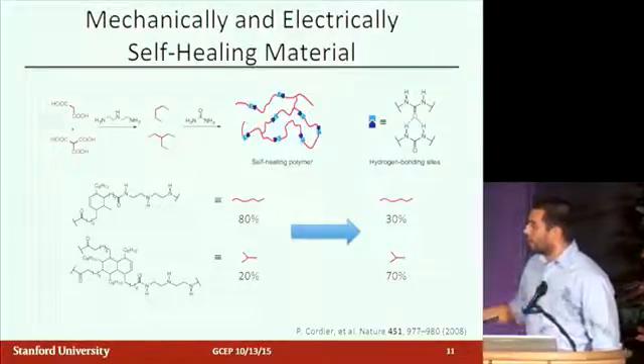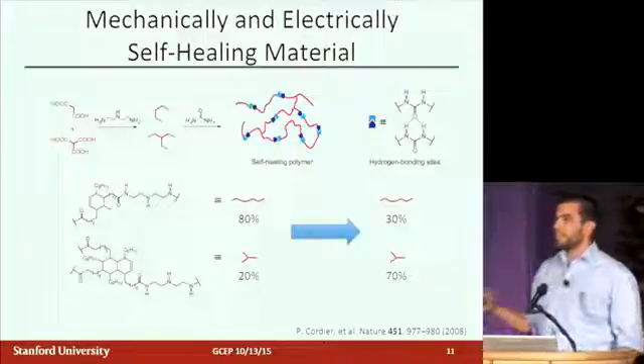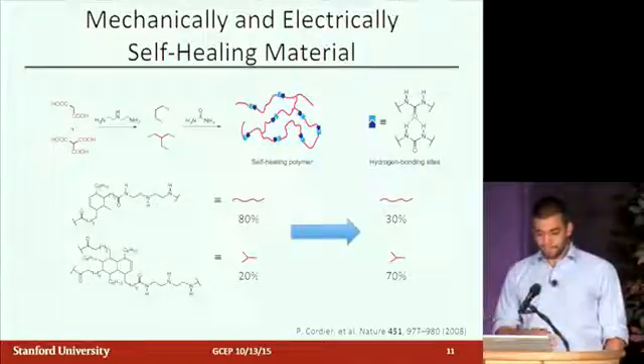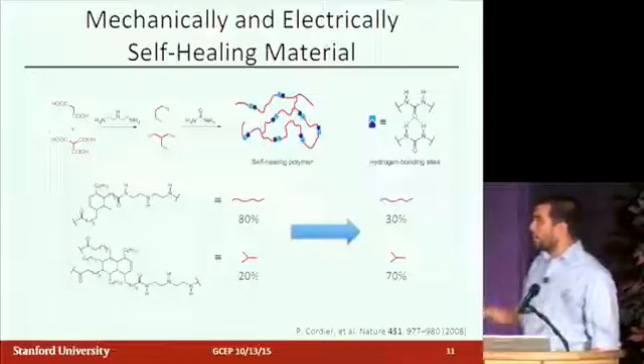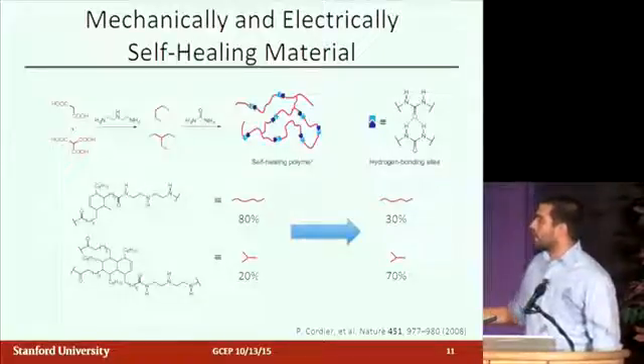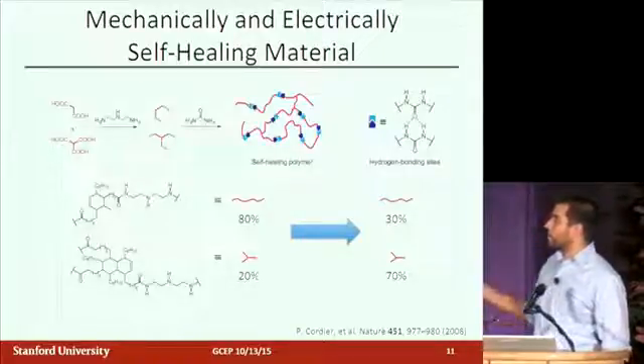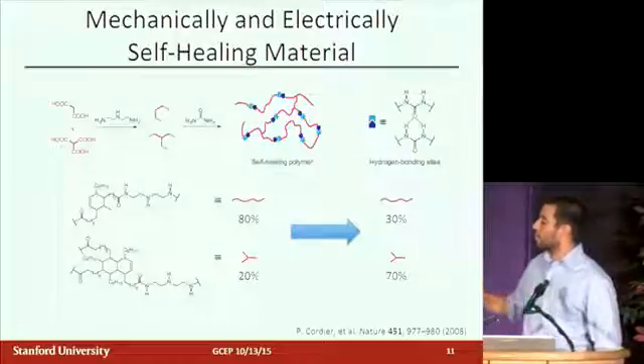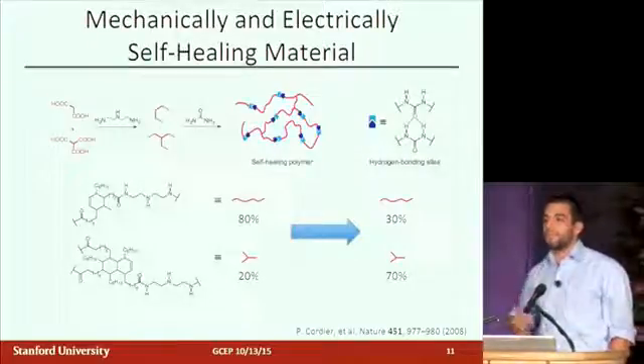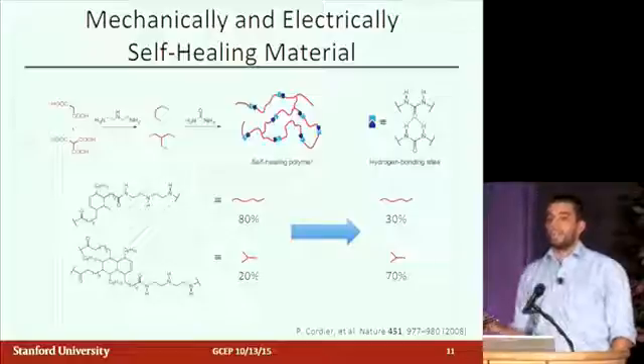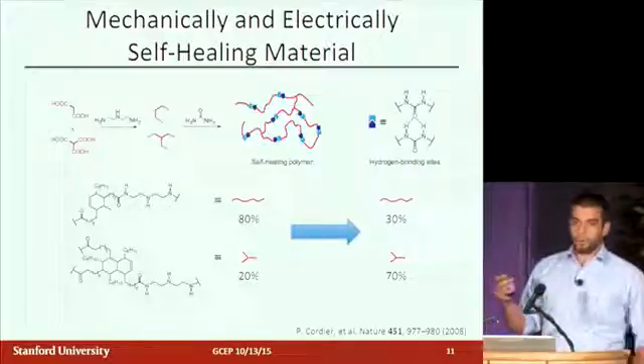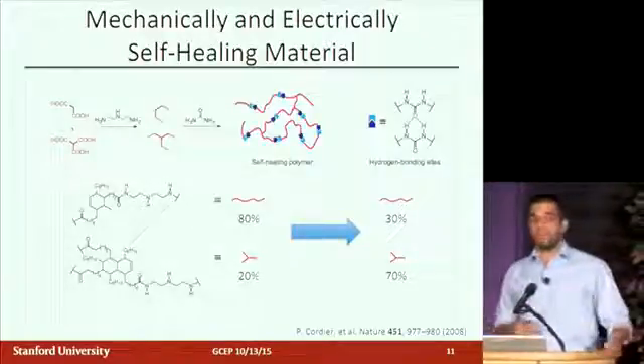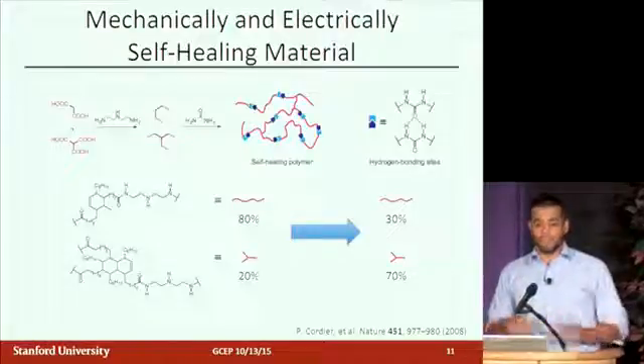And all of the data I've showed before was with this 80-20 mixture, so mostly a linear supramolecular network. What I have been able to do is play with the chemistry, and basically I can have any concentration of trifunctional group between 20 and 70%. And what that allows us to do is really change the mechanical properties. And so we can probe exactly how important the viscous flow is, and what about the self-healing as well.